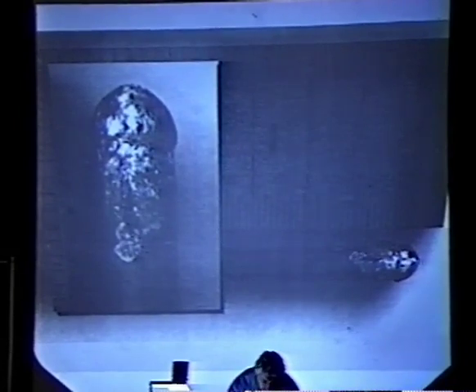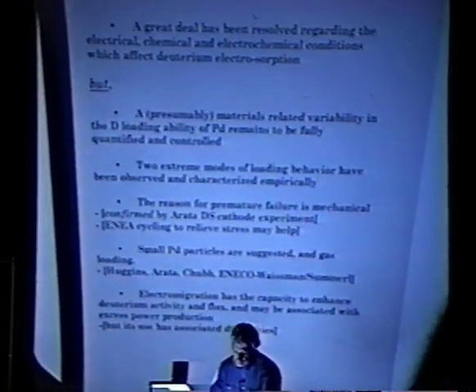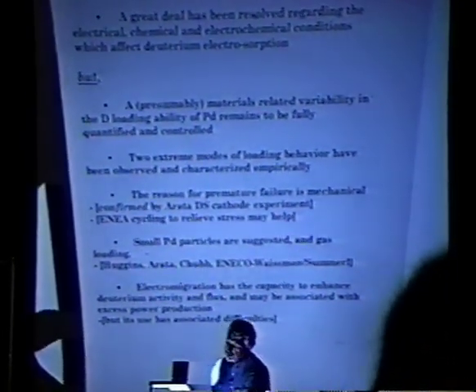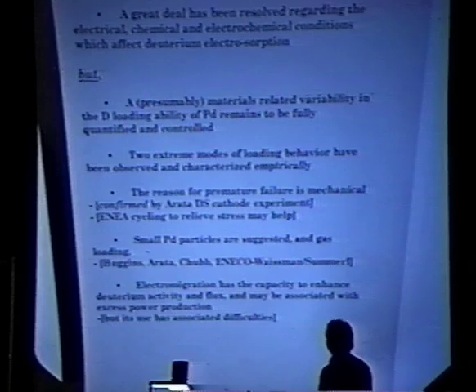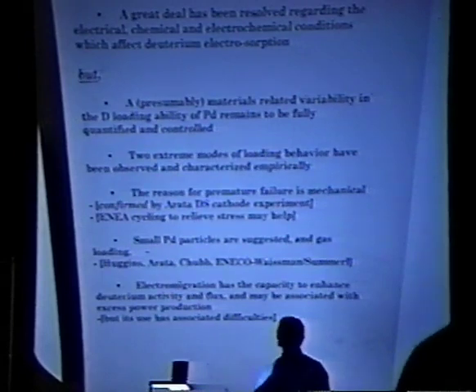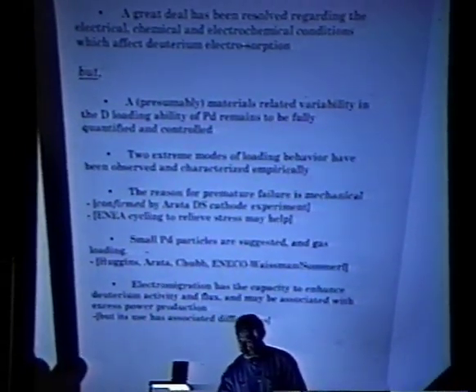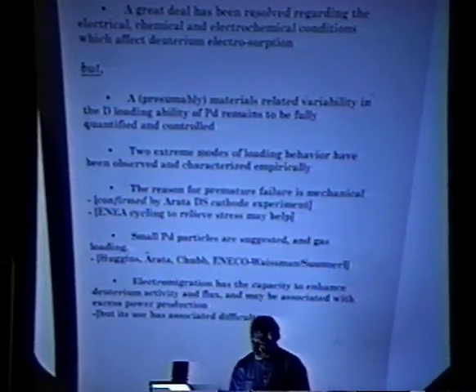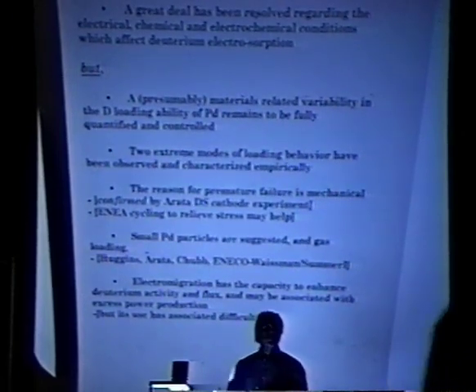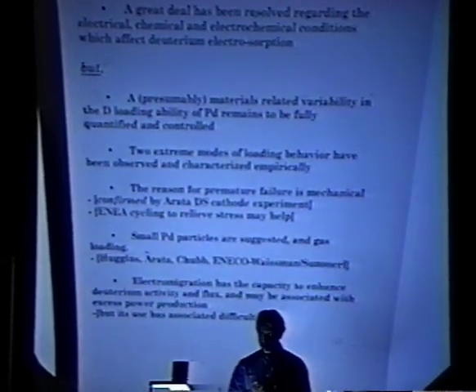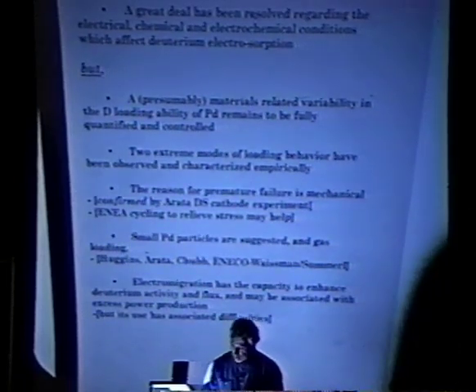I have some conclusions. So, what have we learned? I think a great deal has been resolved regarding the electrochemical conditions which affect deuterium electro-sorption, the loading of deuterium into palladium. But there seems to be a materials-related variability in deuterium loading, which varies from cathode to cathode, which introduces a huge degree of irreproducibility into our experiments.